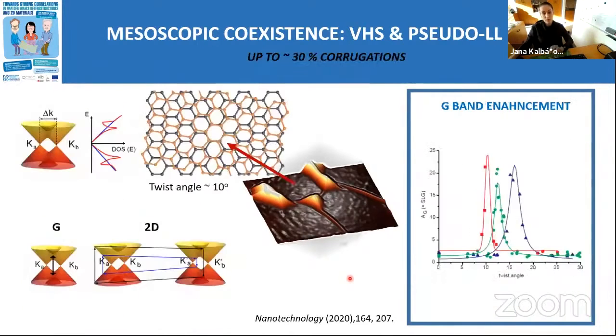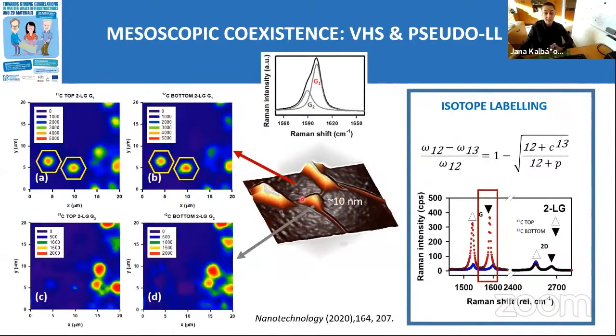In other words, when I switch here to the slide where I try to represent what's happening, in our case, we are simply matching the laser wavelength with the energy separation of the Van Hove singularities, which is created simply because of the specific twist angle between the two graphene layers. So just by tuning the laser energy, we can select on the samples the domains with different twist angles, and vice versa. If we know for which laser we have resonance, we can determine what the twist angle is in these areas.